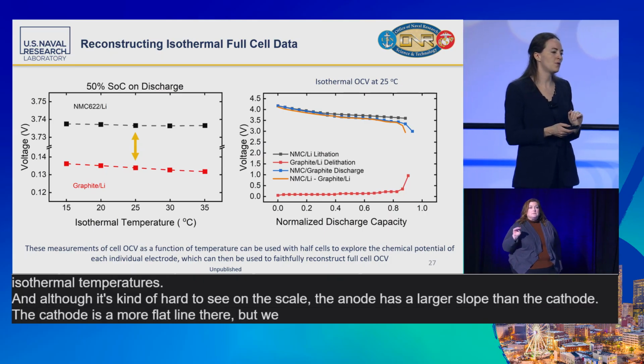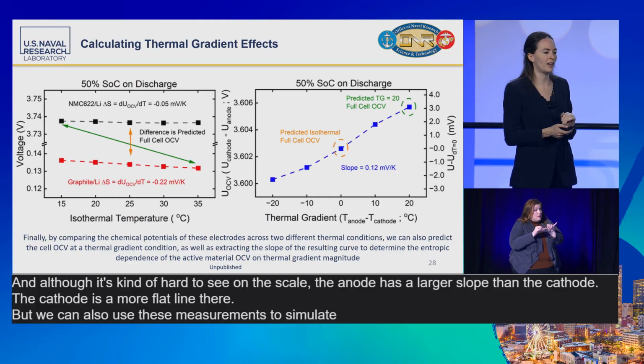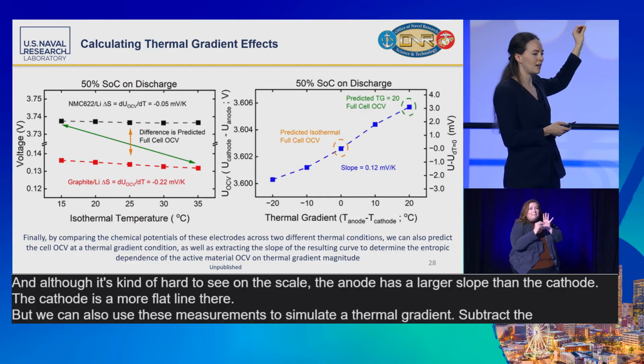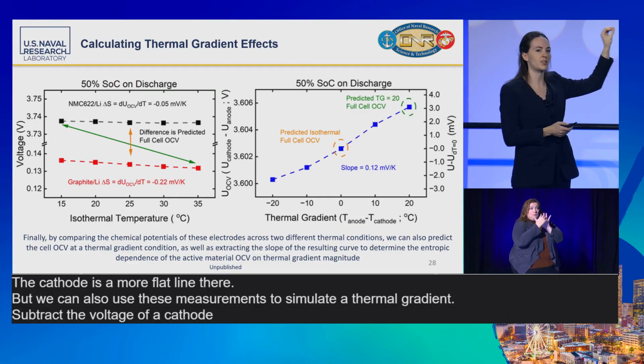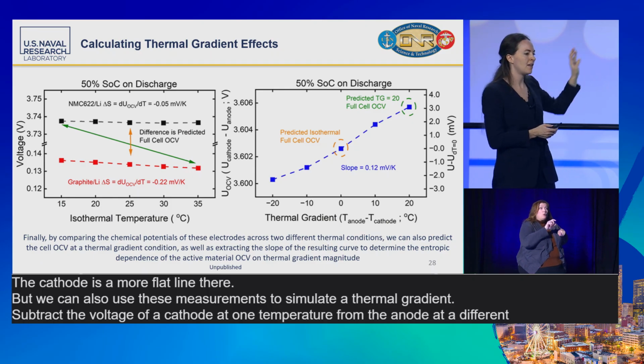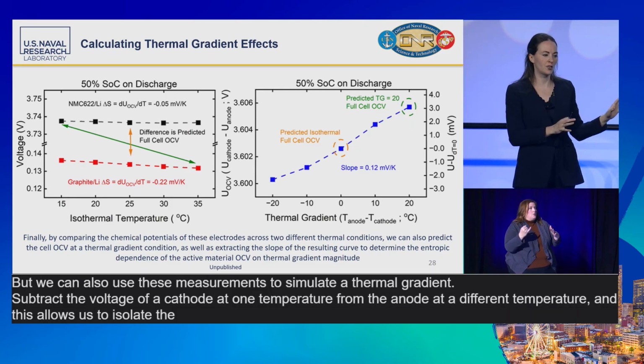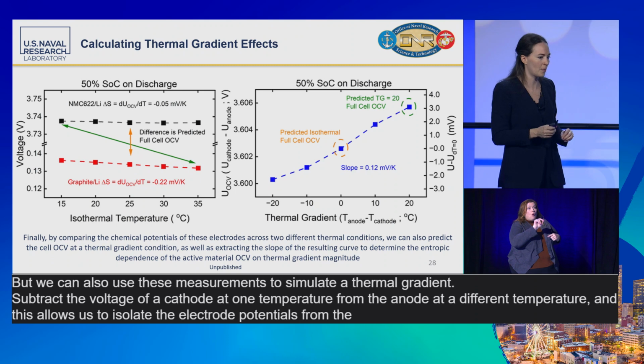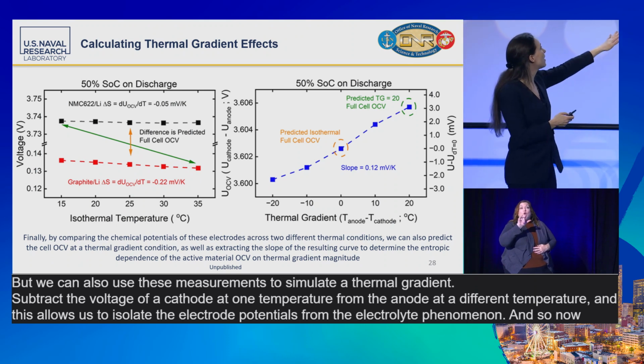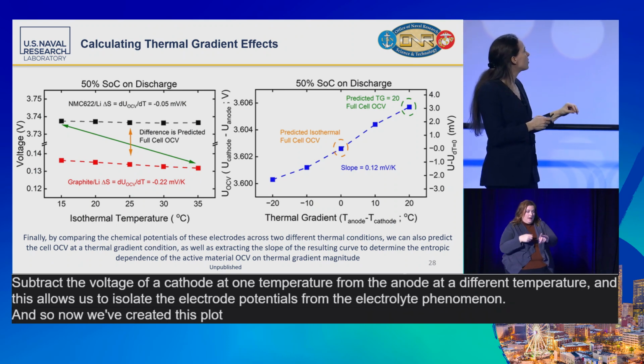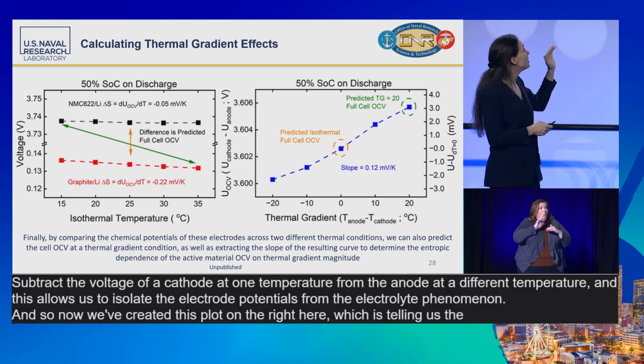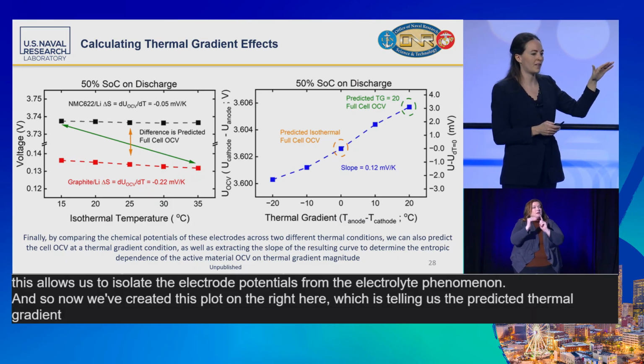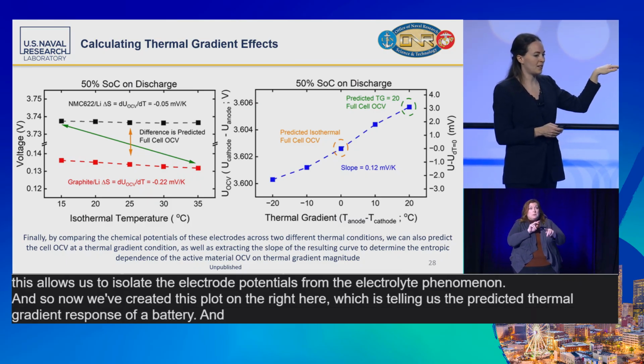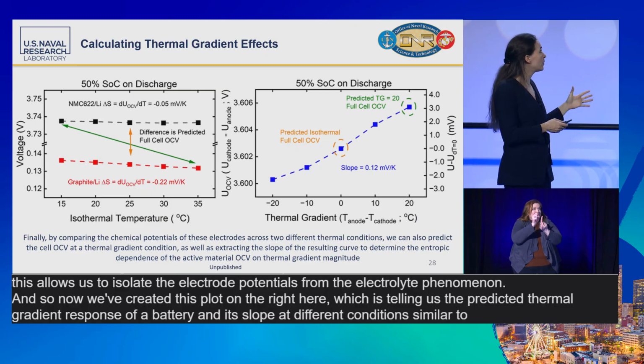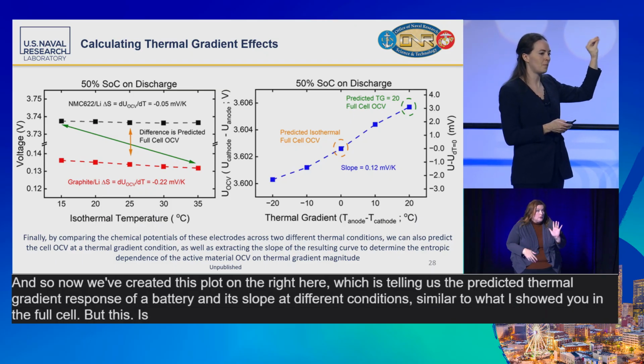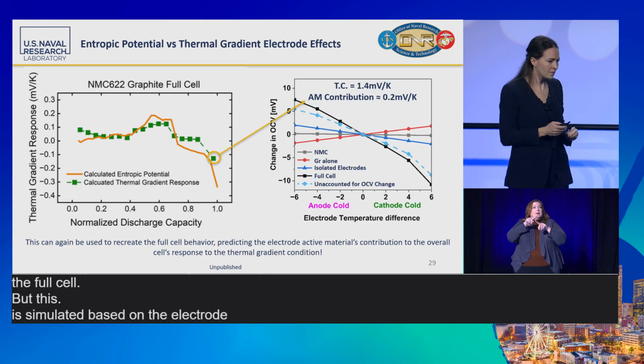But we can also use these measurements to simulate a thermal gradient. Subtract the voltage of a cathode at one temperature from the anode at a different temperature. And this allows us to isolate the electrode potentials from the electrolyte phenomenon. And so now we've created this plot on the right here, which is telling us the predicted thermal gradient response of a battery and its slope at different conditions, similar to what I showed you in the full cell, but this is simulated based on the electrode data.